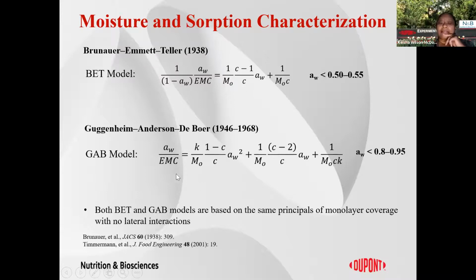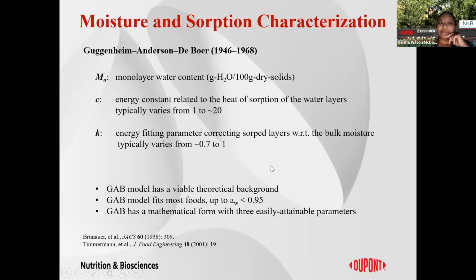A more popular isotherm, or just as popular, but more of an effective range isotherm, is this GAB model. And this GAB model also takes into account both data of the equilibrium moisture content and water activity, but there are three parameters. And both of these models are useful because not only have they been shown to fit a number of different food systems, but they both are based on the same principle in terms of monolayer moisture coverage of absorbed water molecules, but have a physical significance. The individual parameters have a physical significance in the phenomena that you see with the materials.